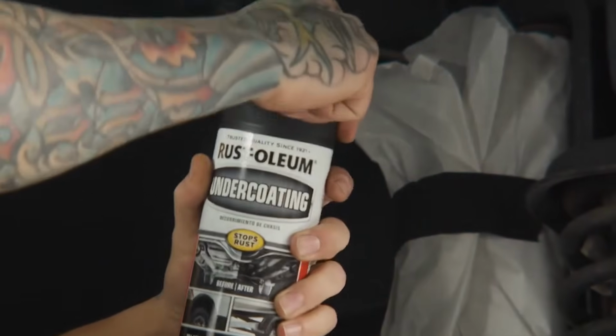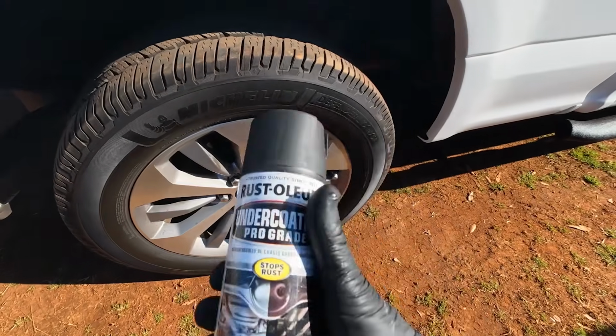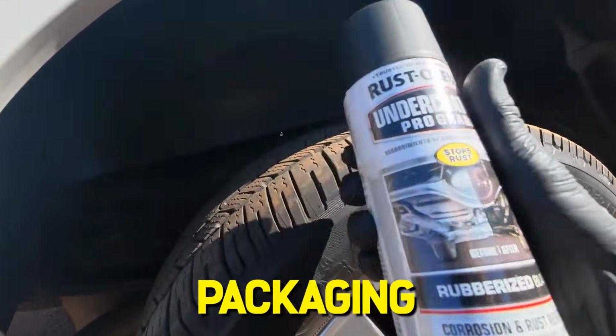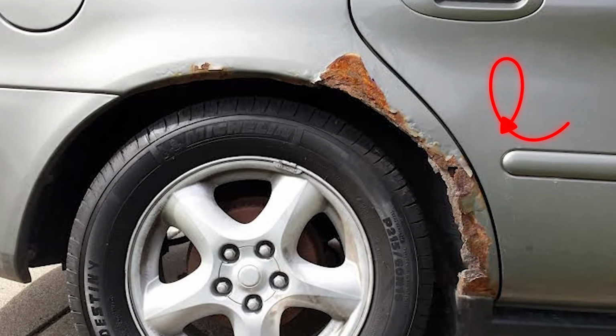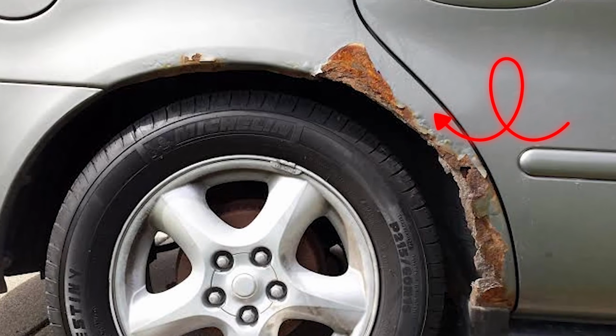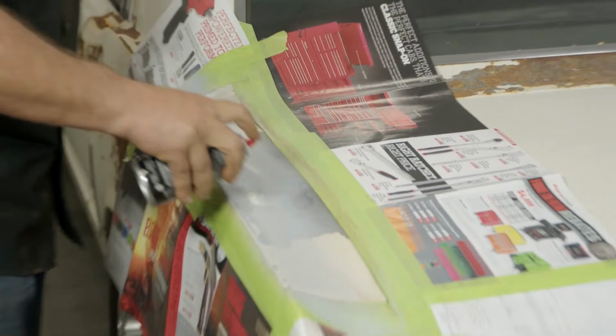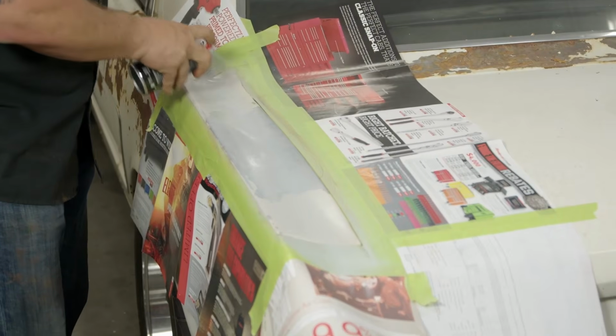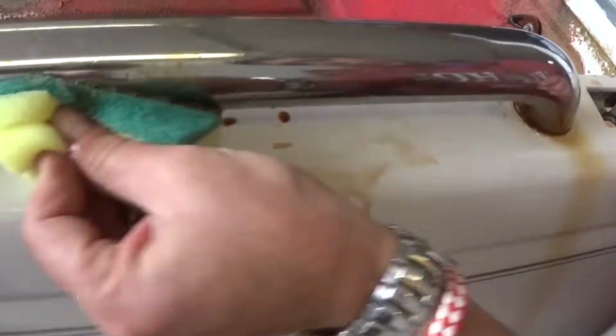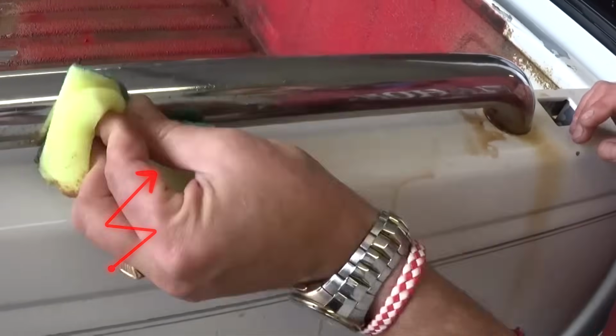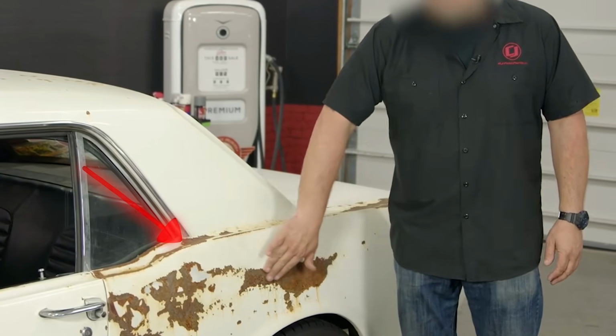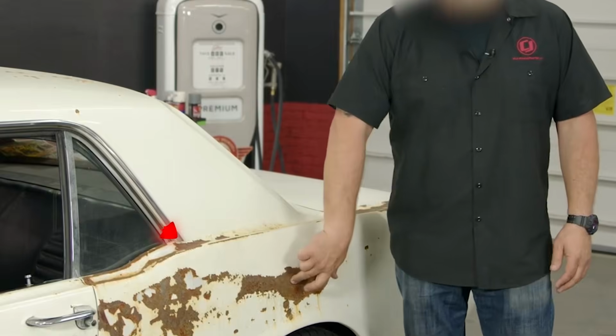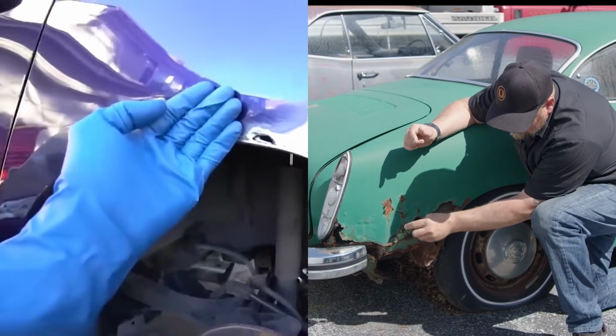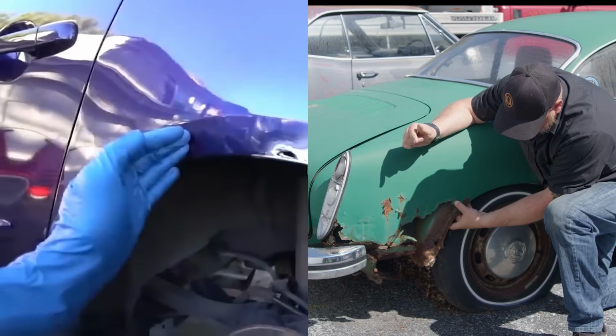That first impression is the most expensive part of this product, because what comes next is what the packaging never mentions. Rubberized asphalt formulas rely on a continuous unbroken film to exclude moisture from the metal surface beneath. When road salt spray and freeze-thaw cycling stress the film, micro cracks develop. They appear at the edges of the coating first, then at any point where the spray coat was thinner than the surrounding areas. Salt water penetrates these micro cracks by capillary action. Once salt water is between the coating and the metal surface, it is trapped. The coating that was excluding moisture is now trapping it directly against the metal it was supposed to protect.